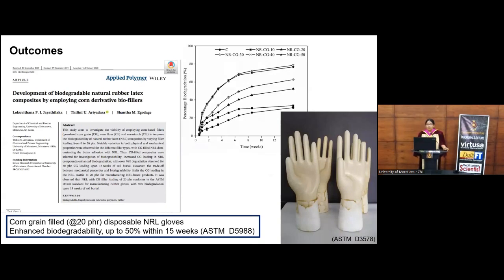We were able to produce disposable gloves by incorporating 20% corn grain starch, and in this case, the test is conducted to find the biodegradability in soil burial in aerobic conditions, and only 50% biodegradability is obtained within 15 weeks. But if you increase the corn grain loading, we can achieve even 80% biodegradability within 15 weeks. However, it gives poor properties and we cannot use it for processing of latex products.